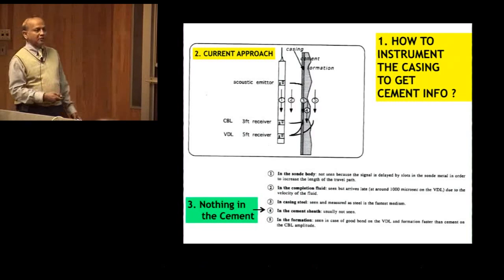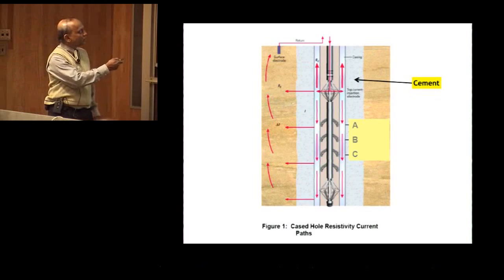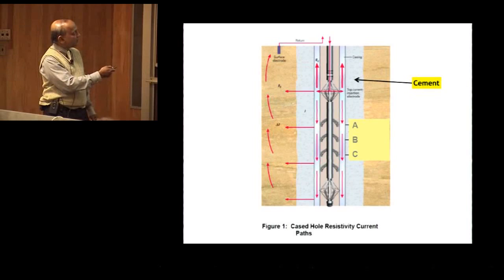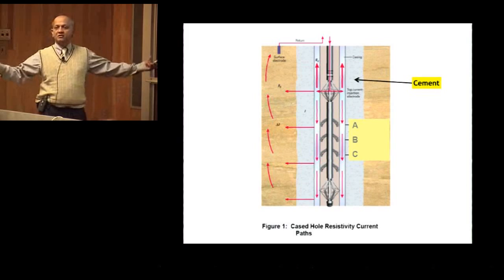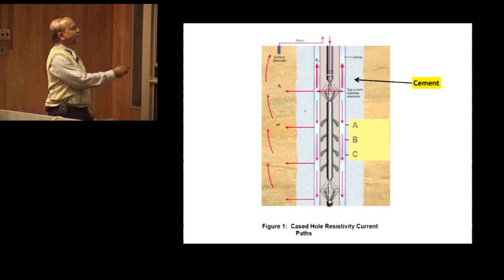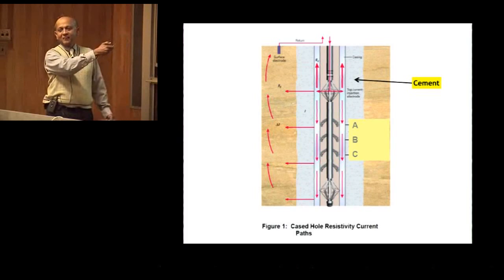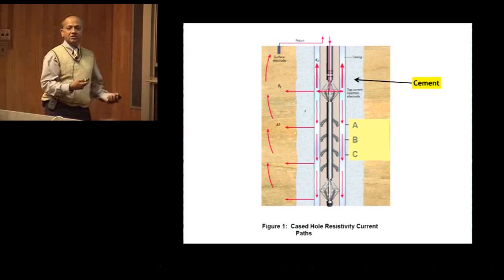Also, they have another method where they lower the probe and contact the casing, then pass current through it and measure the resistivity up here. So what is happening is you have the cement sheath, which is about 2 inches. These formations could be hundreds of feet. And they cannot capture this resistivity because they capture the overall resistivity. This is a current issue.